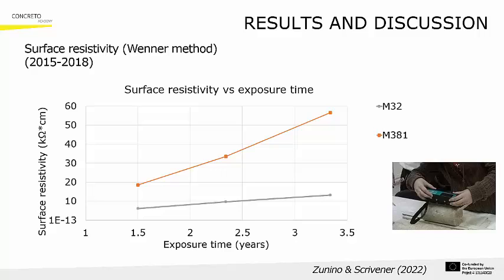Regarding electrical resistivity measured using the Wenner method, values for LC3 concrete were consistently between 2 to 4 times higher than OPC elements. These findings align perfectly with the trends observed in other durability tests and with the published literature.